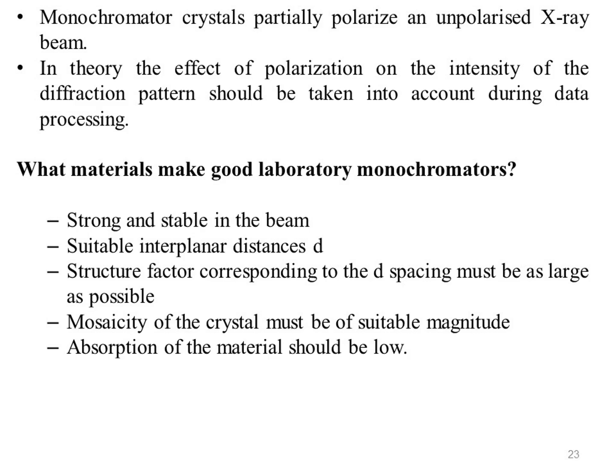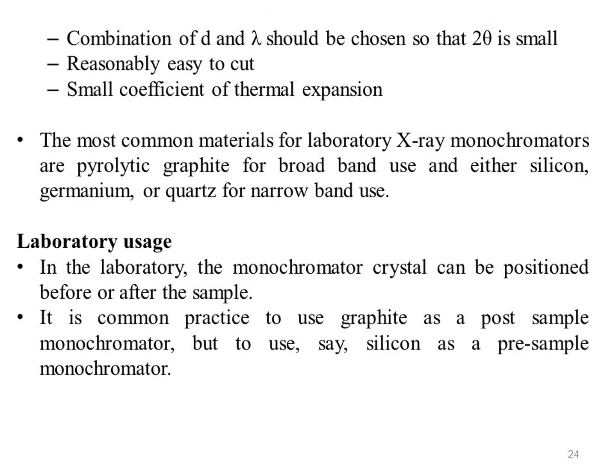The mosaicity of the crystal must be of suitable magnitude, and the distribution of crystal block orientation should preferably be Gaussian. The absorption of the material should be low. The combination of d and lambda should be chosen so that 2 theta is small. This is to minimize intensity loss due to polarization and geometric effect. The crystal should be reasonably easy to cut. The crystal should have a small coefficient of thermal expansion so that the wavelength is essentially unaffected by any fluctuation in ambient temperature that is likely to be encountered.